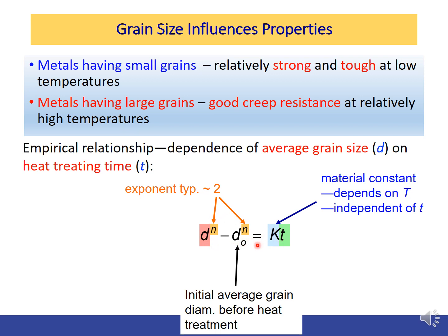treating time. So D, for example, is the grain size we want to have. And D0 is the initial average grain diameter before the heat treatment. And the exponent is typically 2. We use 2 for most metals. And K is a material constant. It depends on the temperature where the heat treatment is carried out, but is independent of the time t.